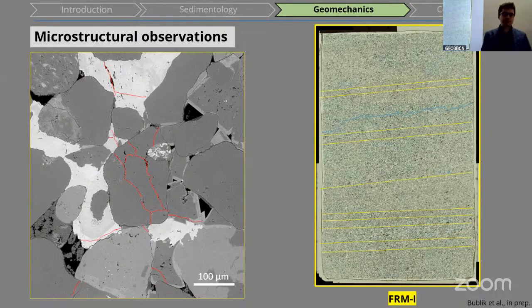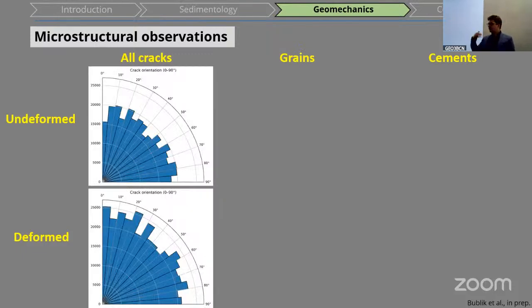And what we do for that is we map cracks. So we have scanned these samples, or we have thin sections of these samples before and after deformation. And what Dimitri has done, he has mapped grains on these images, thousands of grains in many hours, and can then show where these cracks occur in those samples. So what we here have is now some rose diagrams. So if you look at all cracks in the undeformed versus deformed sample, you can see good data, thank God. Our samples have more cracks after we deformed them.